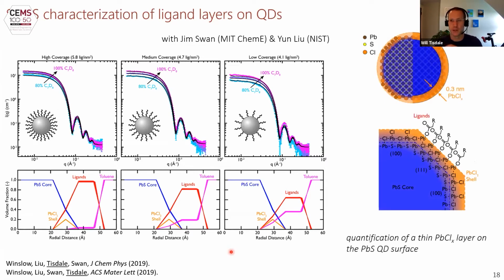The other thing that neutron scattering told us, that we had been asking for a long time, was about the presence of a thin chloride layer on the surface. It had long been hypothesized, from a lot of circumstantial evidence, that quantum dots made in the method that we use, with lead chloride as a precursor, have an insulating thin lead chloride shell that's epitaxial on the surface. It's been nearly impossible to characterize via X-ray scattering and electron microscopy because it's epitaxial and because lead is present both in the core and the shell, and it dominates all of your scattering probes. But the chlorine has a very different neutron scattering cross-section, and we were able to unambiguously measure its presence on the surface.